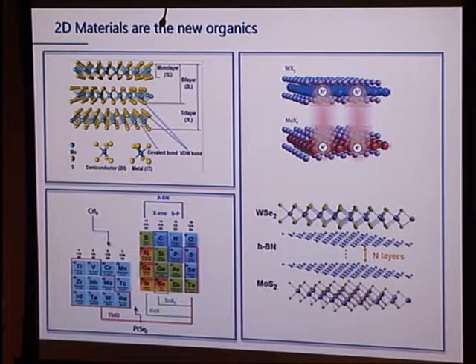where you take some transition metal of some description and you combine it with a chalcogenide, so that would mean sulfur, selenium, or tellurium. That's certainly one option. There are others as well. And those tend to grow in this layered van der Waals fashion, and they have an enormous variety of different electronic properties. And if one of them is not enough for you, you can make so-called heterostacks.